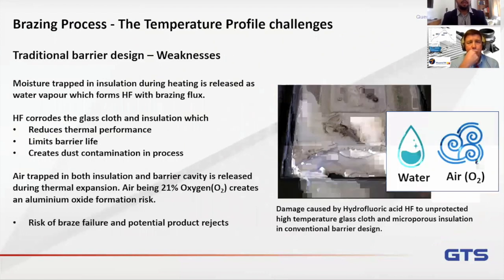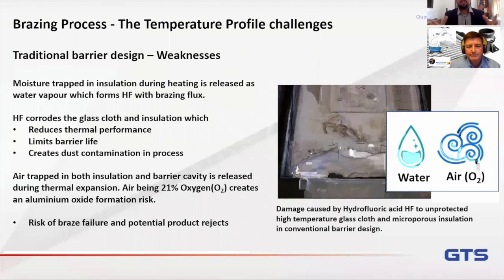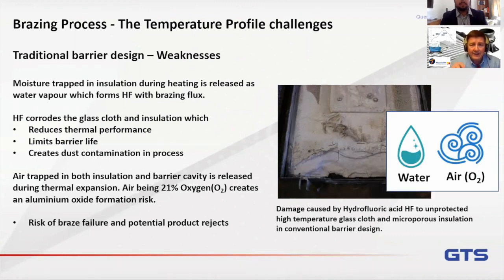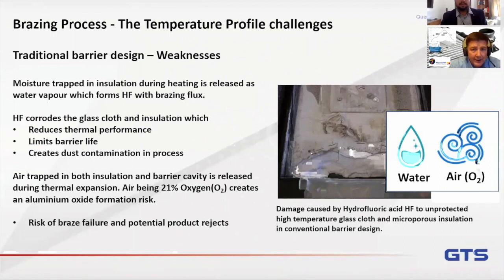Right. Yeah, because the regular thermal barriers that we use are usually focused on traditional heat treatment environments, where in some cases the atmosphere is not a problem, especially when you're doing vacuum. Well, there's no atmosphere, so that's not an issue. But here we need to have in mind the design of the thermal barrier specifically for this type of brazing, right? Correct. And as you can see on this slide, there's a photograph of a traditional thermal barrier, which is what I call a clamshell design. So you've got a lid and a base. The base has the data logger sitting inside it, and there's a glass cloth and the microporous insulation underneath it. And as you can see here, this is clear evidence of where the hydrofluoric acid has attacked the internal materials inside the barrier. It's beginning to eat away at the material, so it's going to be less efficient in its thermal protection.